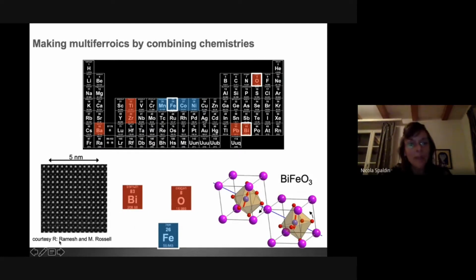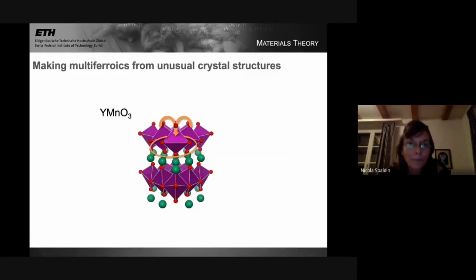But this is a high-resolution transmission electron micrograph from the group of Ramesh. The microscopy was done by Marta Rossell. You see that the white dots here are the bismuth atoms. The very pale gray dots in the center are the iron atoms. You don't see the oxygens in this kind of image. But you can see that this film is essentially perfect. And so with this astonishing ability over the last couple of decades to make really, really high quality oxide films, we were able to achieve this multiferroic behavior in bismuth ferrite. And I'll come back in a little while to look at some of the properties.